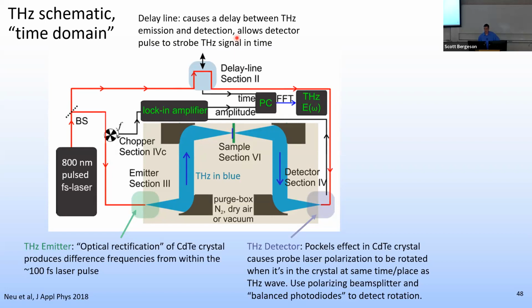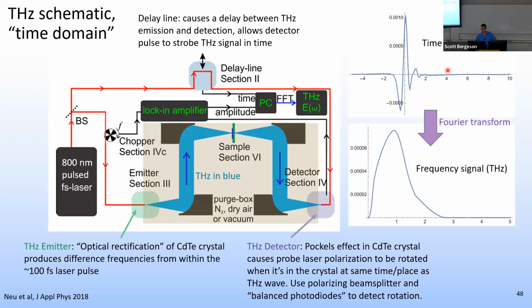There's also a delay line, which allows you to have a delay between the emission and the detection. So you can actually trace out the terahertz beam in time, as the electric field goes up and down, which you can't do with visible light because it goes up and down so quickly. But with terahertz light, the up and down of the electric field happens on the picosecond time scale. This is some actual data I took when I was there. You can do the Fourier transform of this to see the frequencies you're producing, between maybe 0.2 terahertz and 2.5 terahertz. Then you can see how the terahertz gets absorbed or otherwise interacts with your sample.